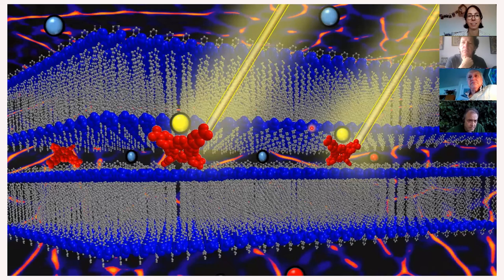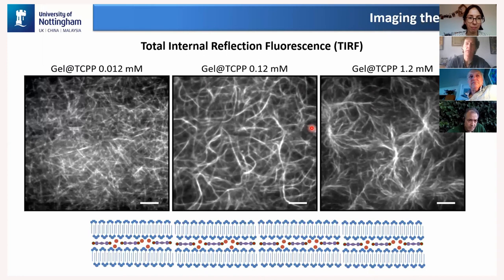Yeah, that's a great question, right? So if you look at this kind of fiber image, for example, which I'm sure is what Philippe is thinking about, those fibers are actually extremely elastic. There's a lot of work now, actually, Philippe. I know it's not your area exactly, but in the area of organic crystals, plastic organic crystals, there's an awful lot of work going on. So they can deform. When we look at the rheology, what we're doing is actually breaking fibers as well.